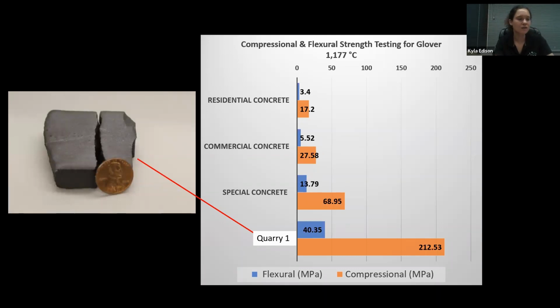After that test was done, we decided maybe if we bring the temperature up a little bit more, that'll change the material, or maybe it'll make it stronger. So they started again with just Quarry 1 material. At the time when they did this, that was the only material that they had. So we sintered at only 30 degrees C more and came out with basically a different material, different in color, different in strength, and also different in the fact that every time that we would sinter, this material would crack.